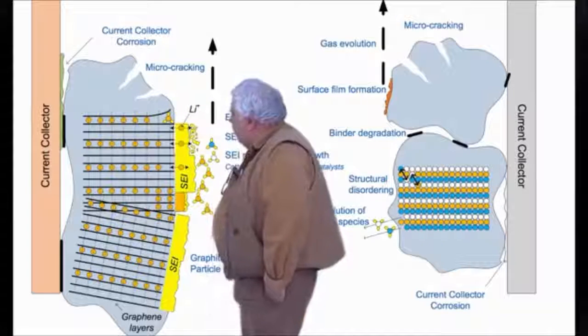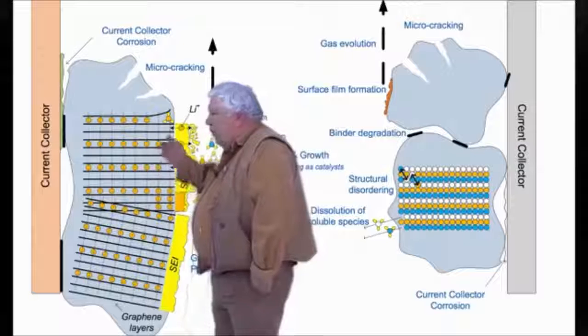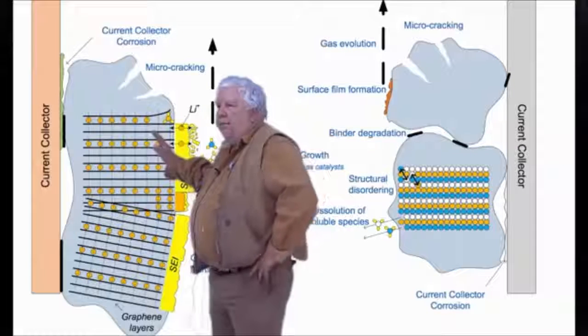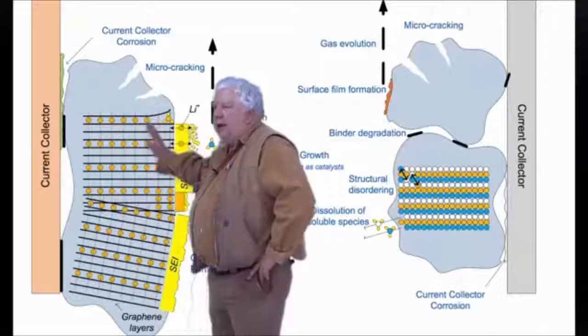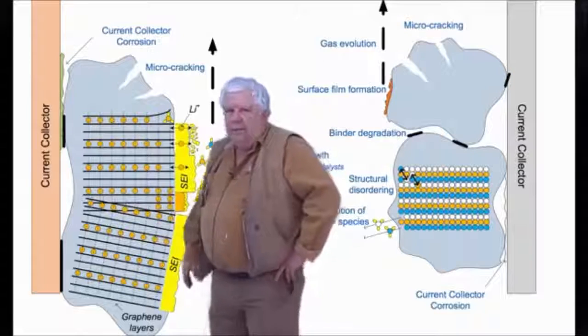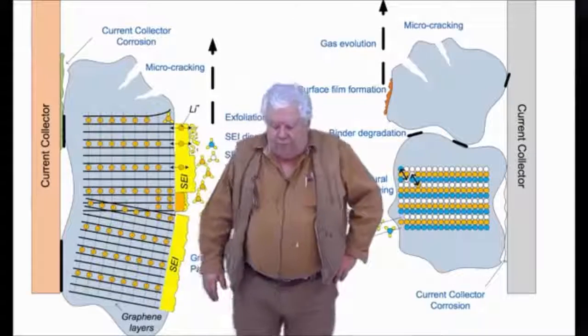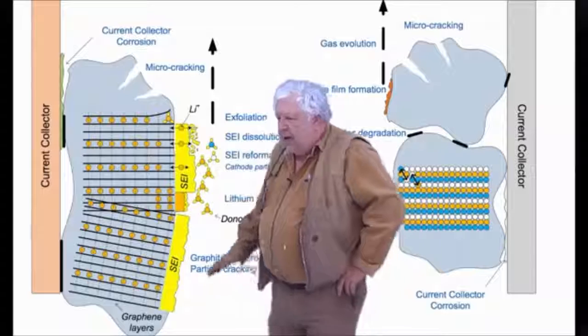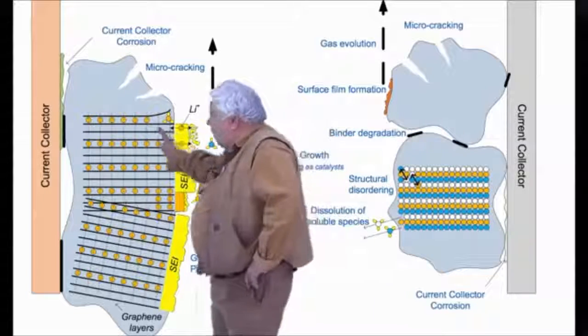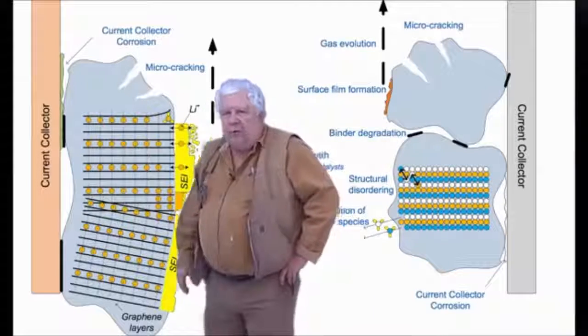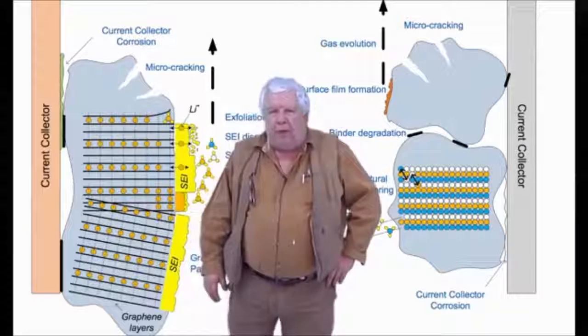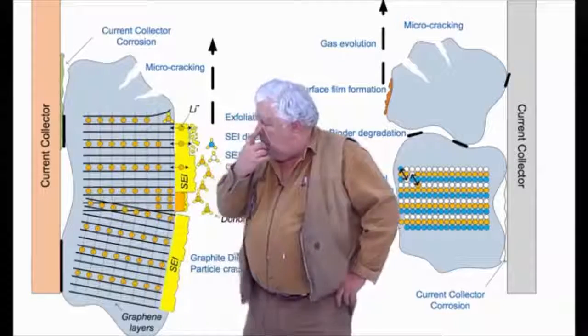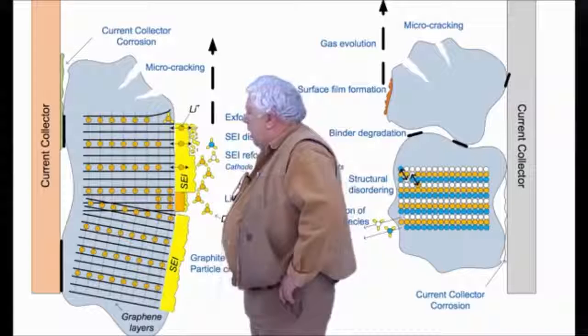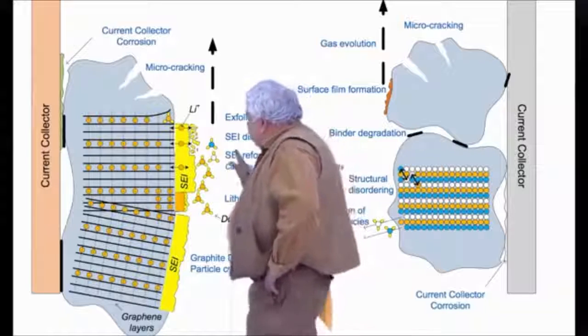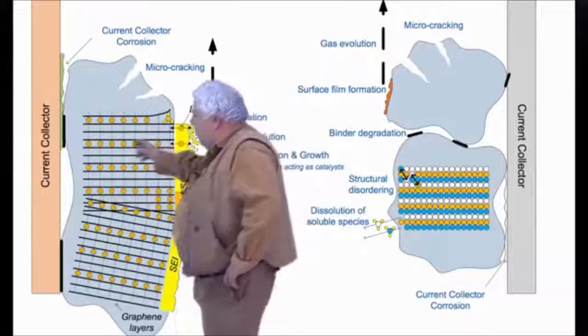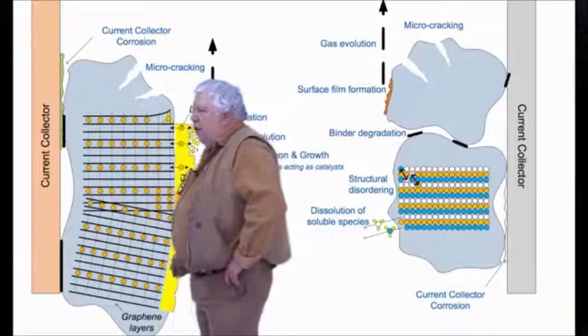And so what happens is that potential drops, and we start to have lithium ions collect on the surface of the SEI, and it can't get through. And as another lithium ion comes along, they combine into a crystalline structure, and we build up lithium plating on the SEI layer. Some of it does get through the SEI layer from that crystalline structure.